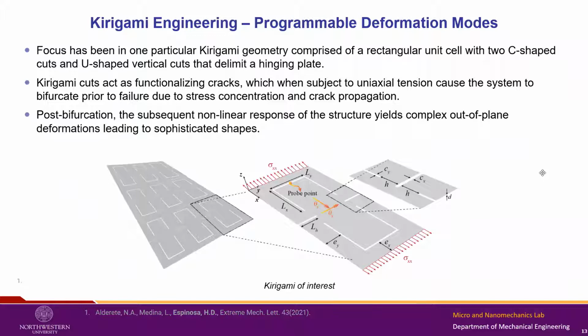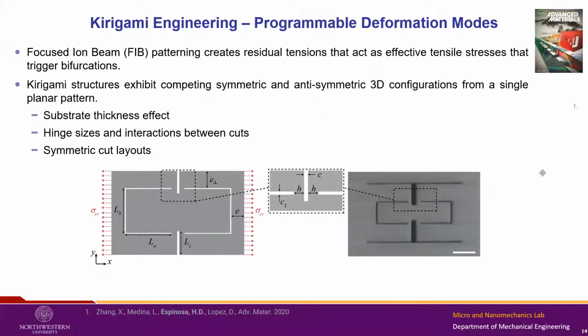Within that subset, we focused on a very simple Kirigami motif, which is basically just a rectangular plate that has C-shaped cuts and then two vertical U-shaped cuts. As I said, when these structures are stretched, instead of failing by crack propagation in the cuts, a bifurcation happens. These structures buckle under tension, and they give way to very interesting nonlinear responses, which, beyond the stress and strain relationships, produce really interesting out-of-plane shapes, which can be used for different things.